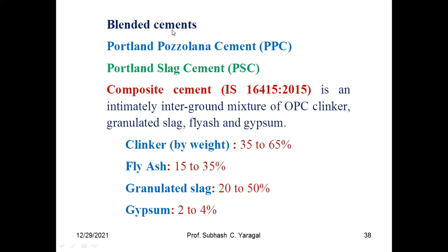So we are talking about blended cements because we have produced Portland pozzolanic cement, Portland slag cement, and Bureau of Indian Standards has come out with composite cements where you have both fly ash and also granulated slag. Both are industrial byproducts. They are no more waste, but they are both value adding to the clinker. So you are only consuming less of the clinker deposit, whereas bringing in these two along with gypsum to delay the setting times. So this is a recommended composite cement, which at least to the tune of 65, if you look at the upper limit, we are getting rid of our normal OPC for concrete production, for cement production.